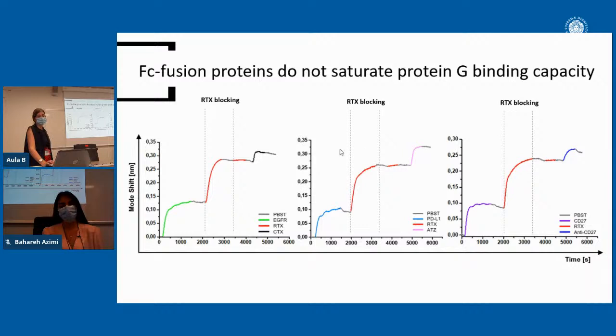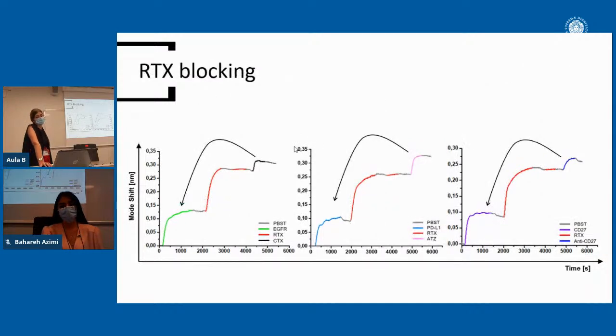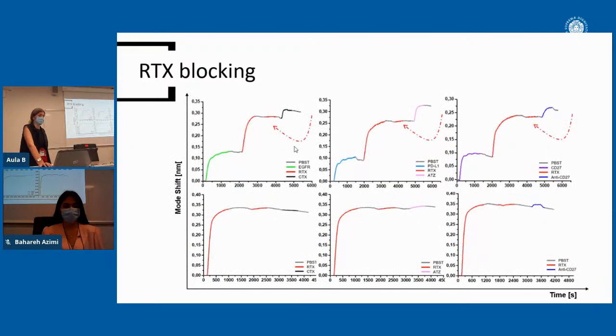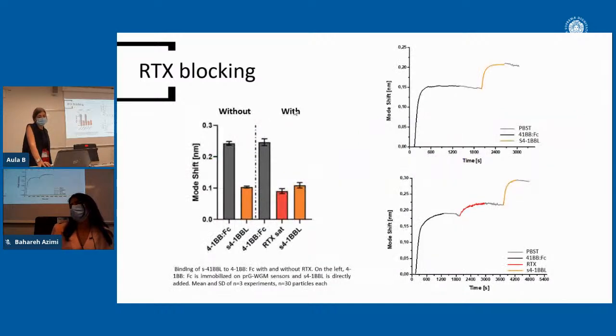So we tried to block the free remaining protein G binding capacity with rituximab before adding the analyte, so that we could measure the binding of the analyte to the corresponding ligand. Of course, we performed several negative control experiments, and in all cases we found that the binding of the analyte that we detected was to the ligand. And just to check that the presence of rituximab on the sensor surface is not interfering in the interaction, we tested two different binding pairs.